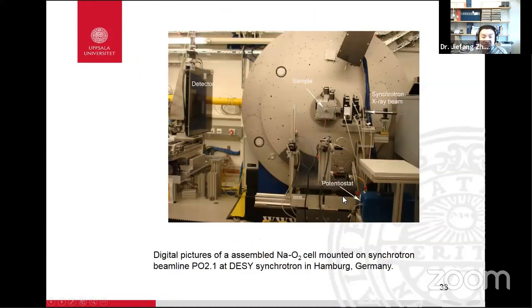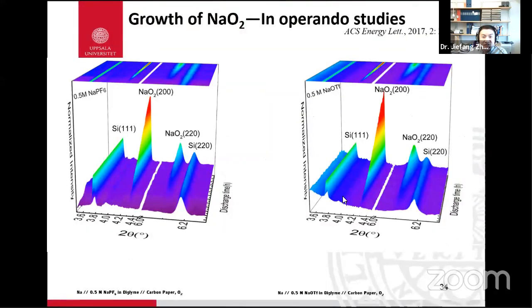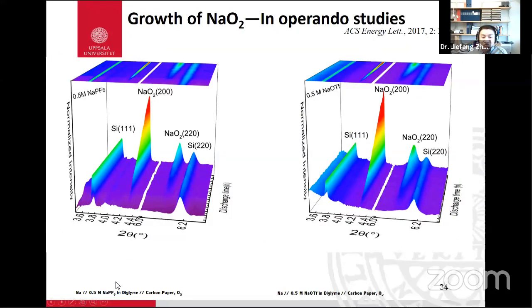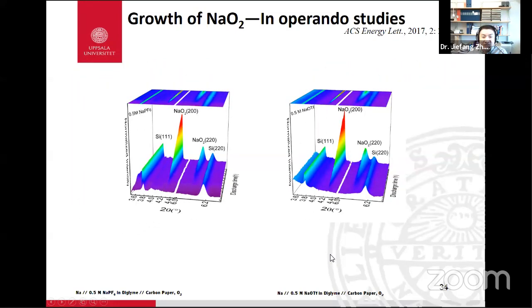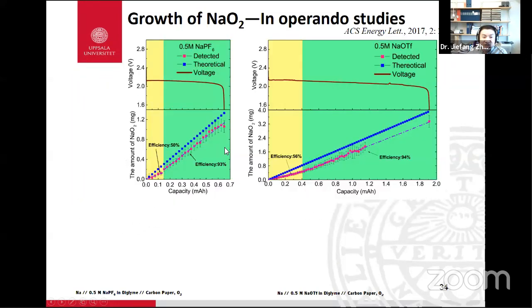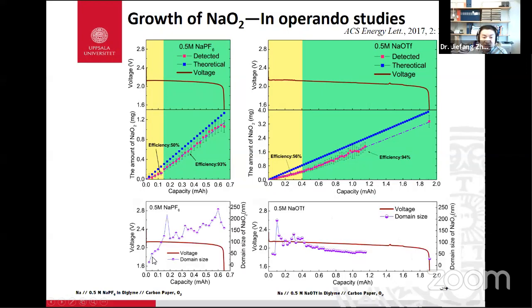So we use the same cell for the sodium oxygen battery. The first work is we compare two different electrolytes. One is NaPF6, another is NaOTF. You could see that in both cases the discharge has high efficiency, but NaOTF has higher capacity. Comparing the domain size, in NaPF6 it just increased continuously, but for NaOTF it increased at the beginning, then decreased.